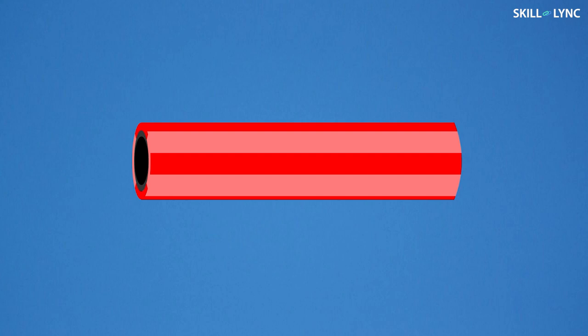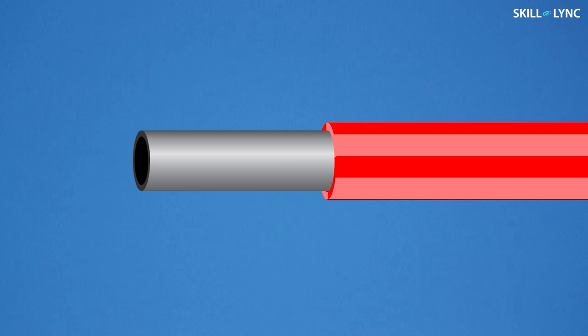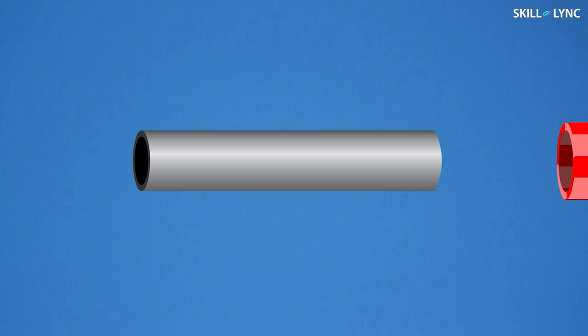During this process, the lighter elements such as impurities and bubbles tend to accumulate on the inner surface of the castings. This can cause a variation in properties of casting throughout its thickness. To avoid this, the inner surface of the casting is machined or grinded, and hence, a smooth casting with the required properties is obtained.